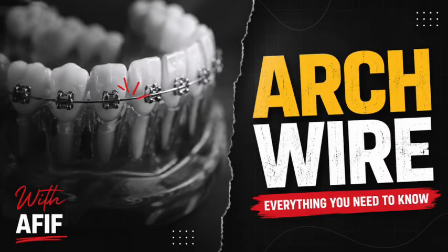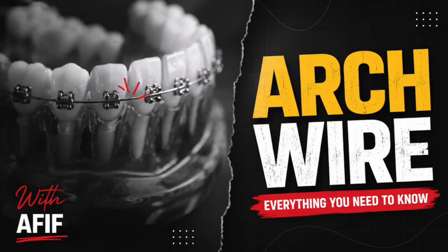And the thermodynamic research also highlighted another crucial phenomenon in these memory wires called hysteresis. Hysteresis. It sounds like a complicated physics concept. A little bit. How does it apply to a wire in a patient's mouth? It's a term that describes the energy loss during the phase transition. Energy loss. In practical terms, it means that the loading curve and the unloading curve on our stress-strain graph do not perfectly overlap. Okay, meaning what? It takes more force to trigger the transformation into martensite than the wire gives back when it transforms back into austenite. So it's not a perfect one-to-one exchange. Right. Clinically, the orthodontist might have to push a little hard to engage the wire into the bracket. That's the higher loading force. Right. But due to hysteresis, the wire pushes back on the tooth to move it with a much lower, dampened, biologically safe unloading force. It's an additional layer of biological protection built right into the thermodynamics of the alloy.